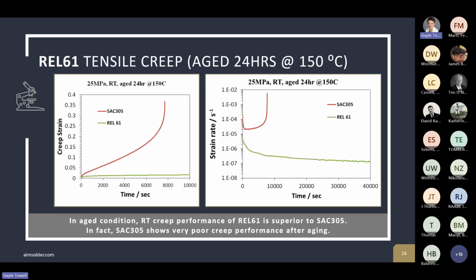This is a tensile creep test. So solder aged for 24 hours at 150 Celsius. And on the left hand, we have creep strain versus time. On the right hand side, we have the strain rate. And we're comparing SAC305 with REL61. And we see that the REL61 tends to have much better creep performance. There's a dramatic difference in these two graphs here. So the creep performance of REL61 is superior to that of SAC305 after thermal aging.